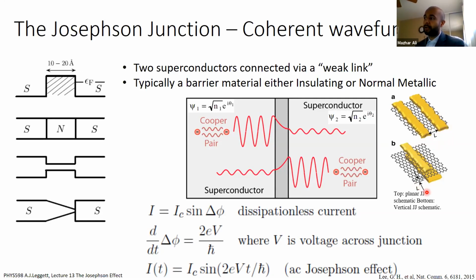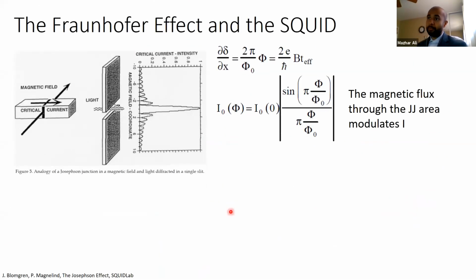Now, with an insulating barrier, the more typically easier approach is to go up and down, especially if you can make a very thin barrier by utilizing layered materials that, like I said, we can exfoliate and grab just a couple of layers at a time. So again, the channel length in the vertical JJ, and from now on I'm going to refer to Josephson junctions as JJs just to speed things up, can be much shorter, and so you can use a good insulator.